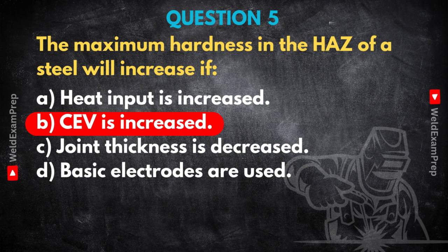Things like requiring a higher preheat temperature before welding starts. Right, slow down the cooling from the start. Exactly. Maintaining minimum interpass temperatures, not letting the part cool down too much between weld runs, and potentially specifying post-weld heat treatment, or PWHT, to temper that hard structure afterwards. All these actions are aimed at controlling the cooling rate, preventing the formation of excessive martensite, and reducing the risk of hydrogen cracking. The CEV isn't just a number. It's a predictive tool for ensuring weld integrity.